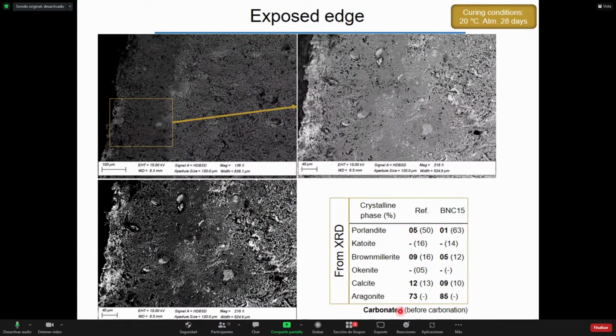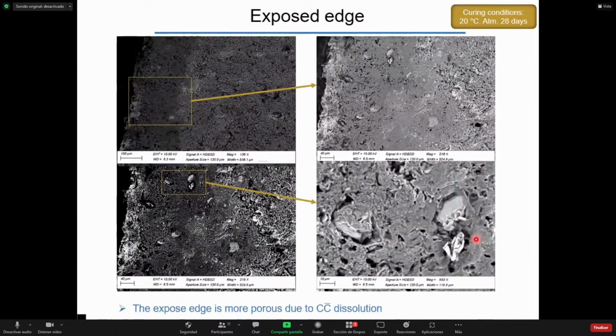Here the black numbers are carbonated values, and in the brackets we have the values before carbonation. From here, we can see that the exposed edge is more porous due to the calcite dissolution, and this reduced the stiffness of the material that we saw in the triaxial tests.